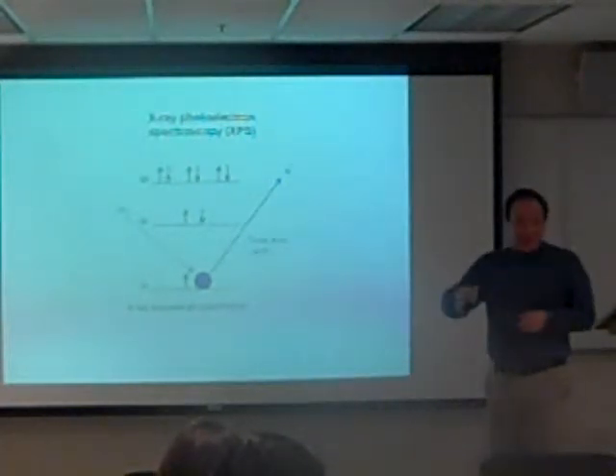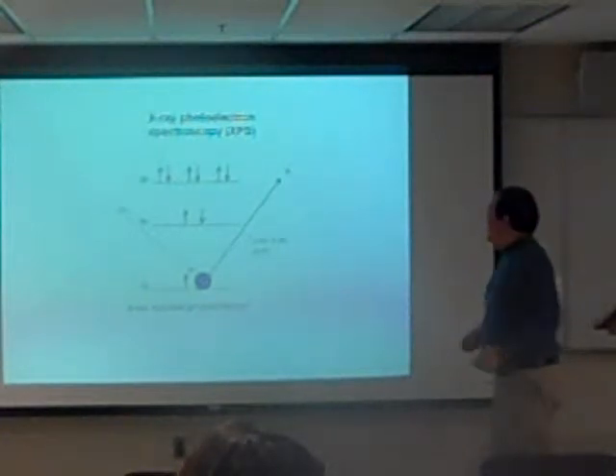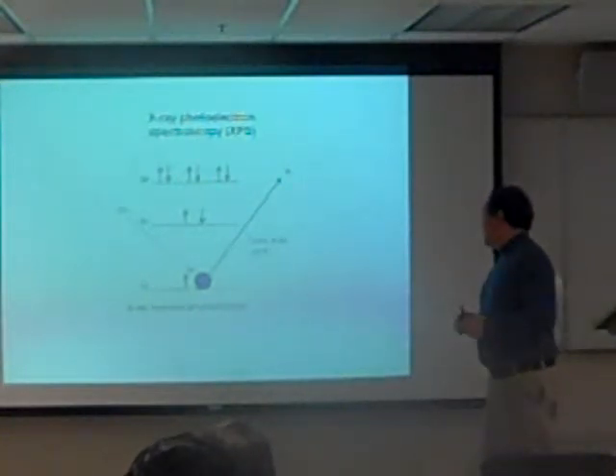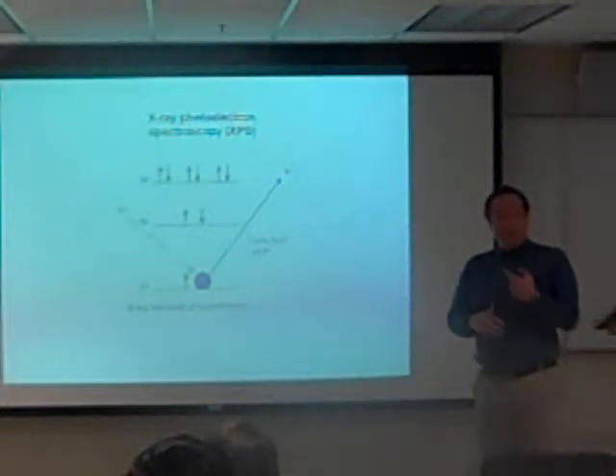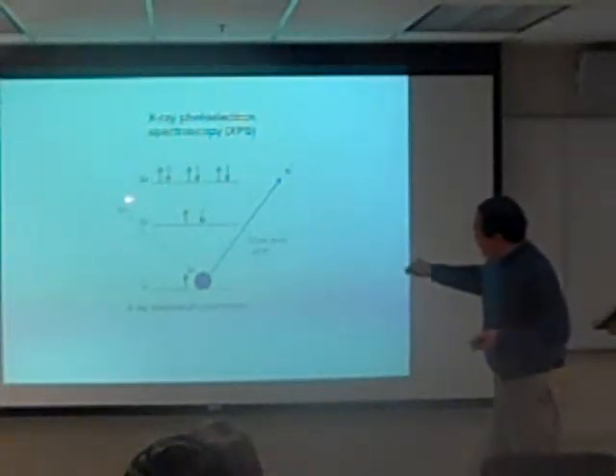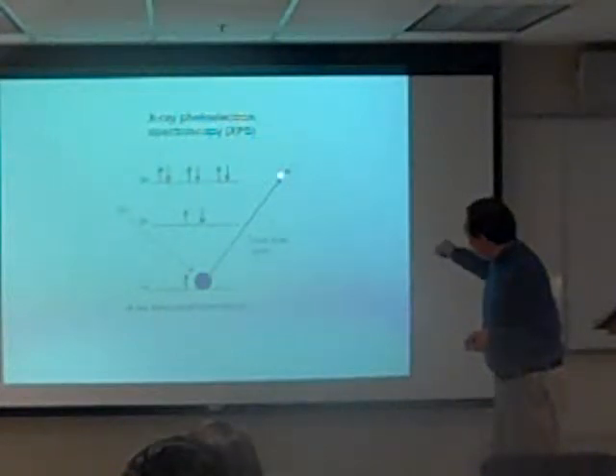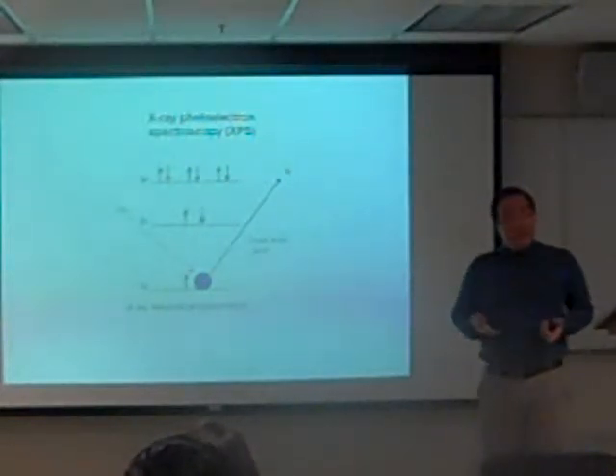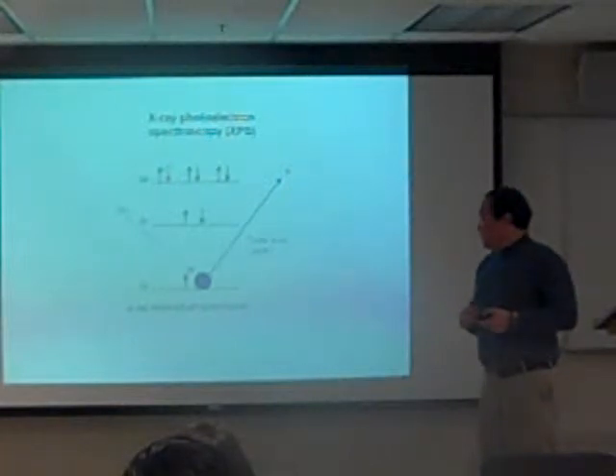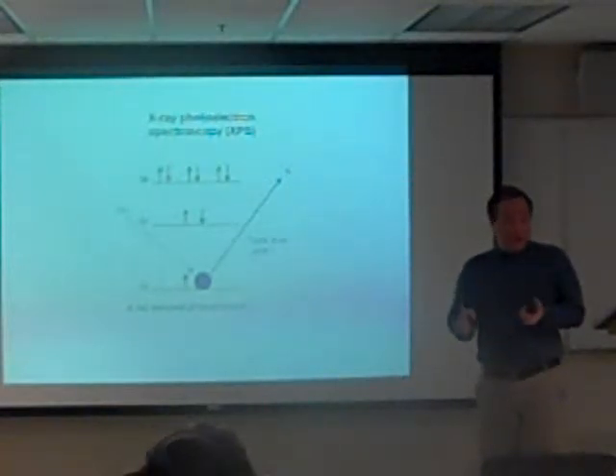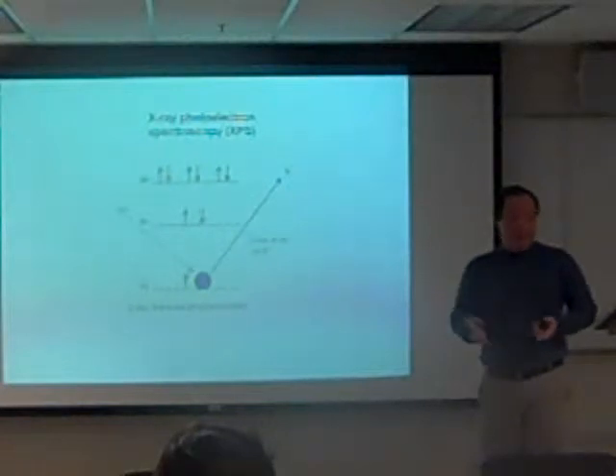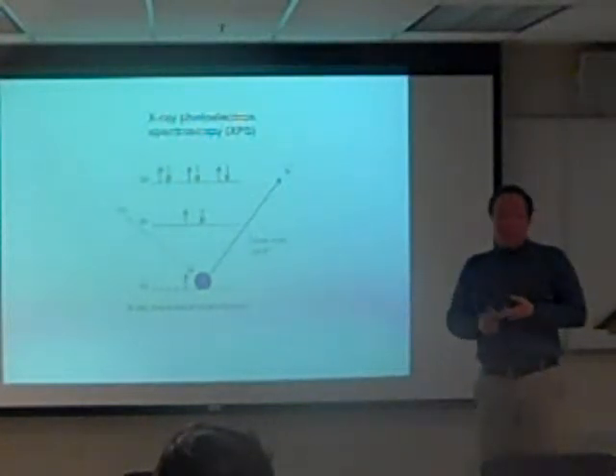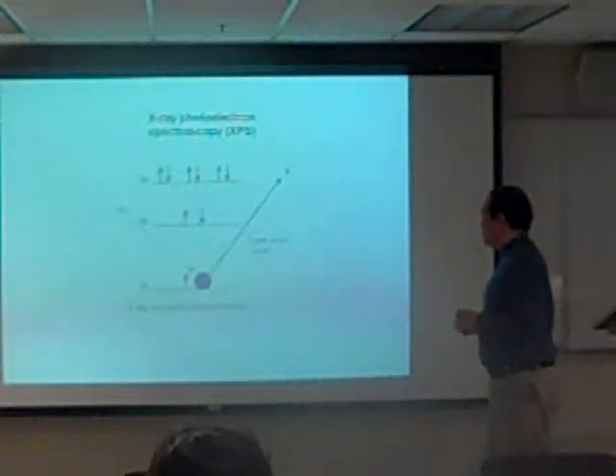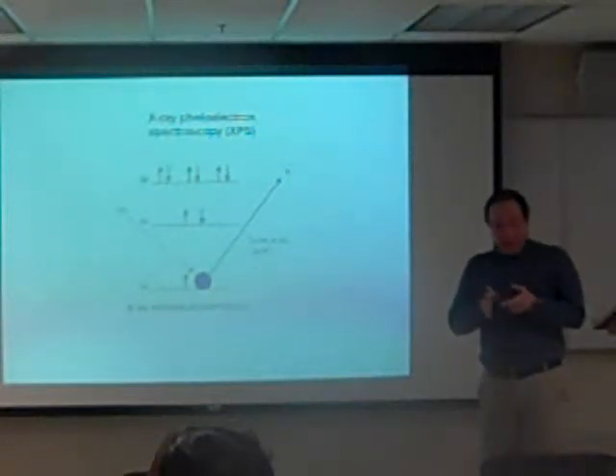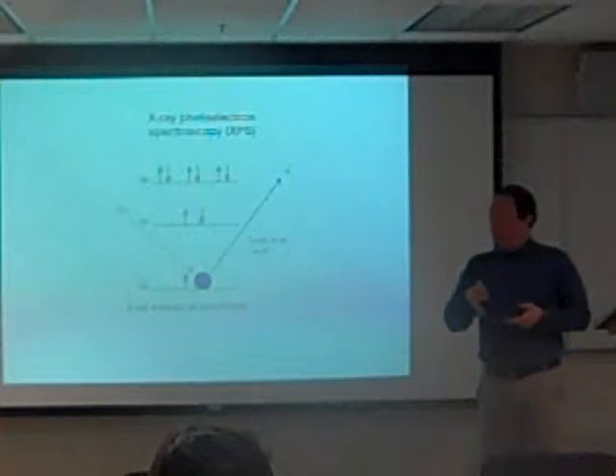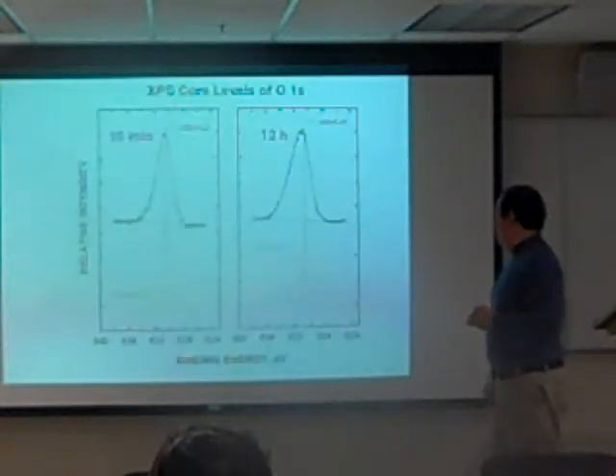Inside that chamber, we see the X-ray gun. What happens inside there? Well, XPS is a technique based upon the photoelectric effect. You shine X-rays here, it knocks off a core electron, and there is no damage to the nucleus of the atom. You're only sampling the outer core of electrons. So you can do non-destructive elemental analysis. You can also do chemical oxidation state identification. That's what we will rely on to identify the different calcium phosphate phases.